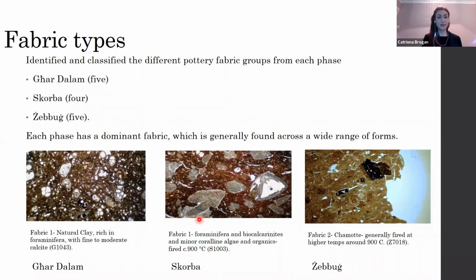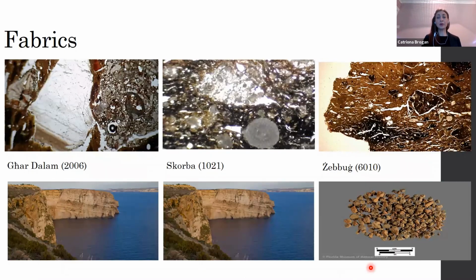So this just gives you an idea of the overall appearance of these three main fabrics that occur in each of the different phases. And while the pottery from each phase shared a number of ingredients, there are very common materials that appear in each of them. Stuff like calcite appears in basically Ghar Dalam, Skorba and Żebbuġ. Stuff like the forams appear in it. These materials are common throughout, and this is probably because they are quite prevalent in the landscape, provided that we can use the provenance analysis to definitively say that these are Maltese pots.